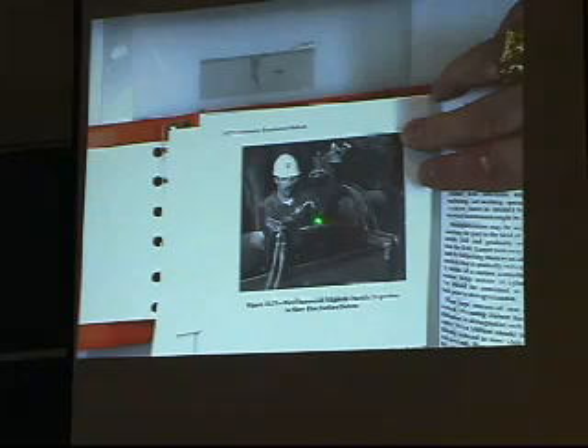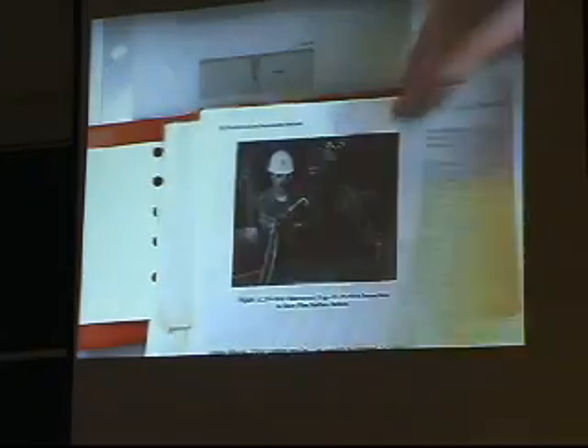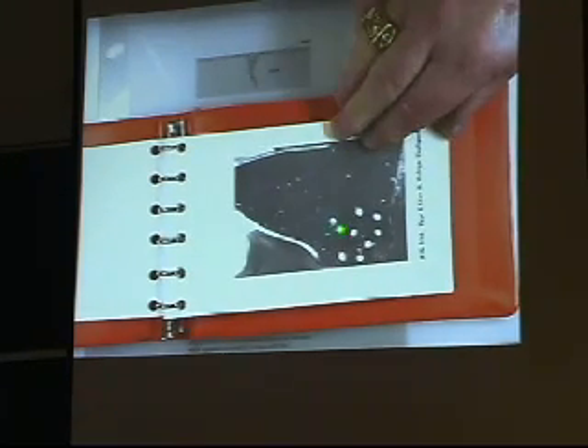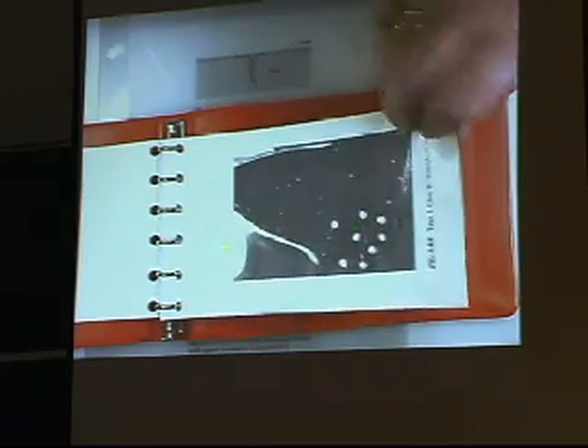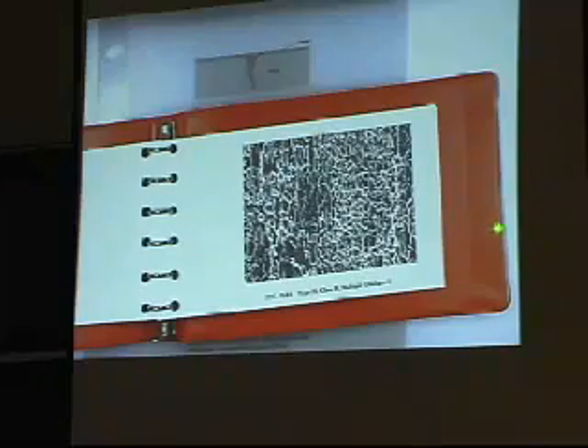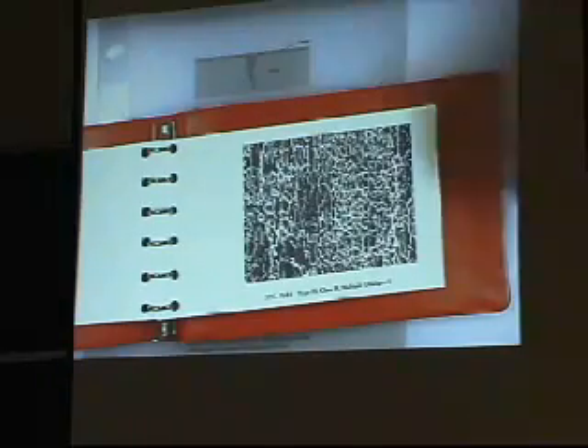He squirts that on, and it has little magnetic particles, and the thing is magnetized, and up here he has an ultraviolet light behind him that he'll turn on, or actually it's probably already turned on. And he'll look at it, and so this is basically some spots and a crack that's shining back in ultraviolet. This is also ultraviolet. Here's something that's got a bunch of surface cracks. This is probably from grinding and overheating the material, it's like a dried riverbed on the surface.